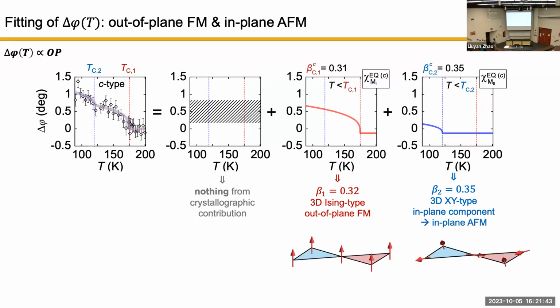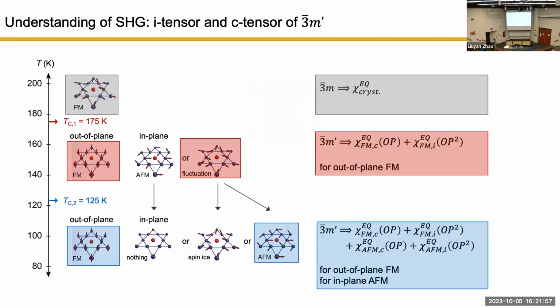So that's this picture. But the second one is XY type, meaning that the spins prefer to be aligned in the plane. So our data is most consistent with this kind of all-in, all-out spin texture in the Kagome lattice. To form a collective picture, what happens for this magnet is that it is a paramagnet at high temperature. Below 175, the out-of-plane component forms the ferromagnetic order. The in-plane component is fluctuating at that moment. Then below 125, the out-of-plane component remains, but the in-plane component goes from a dynamically fluctuating situation into an all-in, all-out state. So at low temperature, your spin is doing this: most of it is out of plane, but you have a cant into the in-plane. And when you plot the in-plane one, it's all-in, all-out.